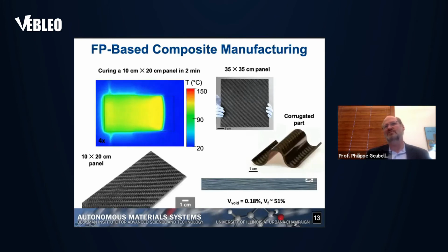And so here's what this panel is about. We made some larger panels. We made panels of different sizes. And then we actually look at the quality of the composite panel that we create by looking, for example, at the void volume fraction and observe that the void volume fraction remains very, very small, in this case 0.2%. The fiber volume fraction for this particular process was about 50%.